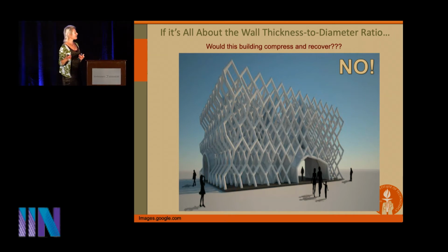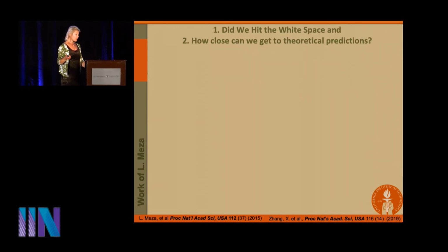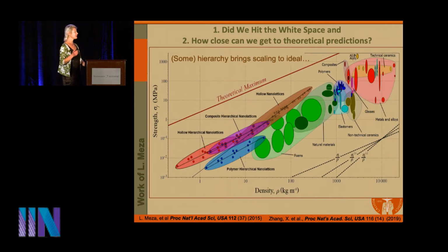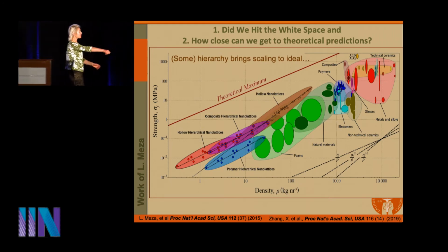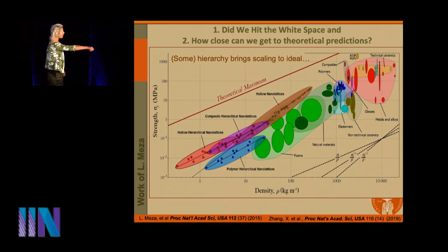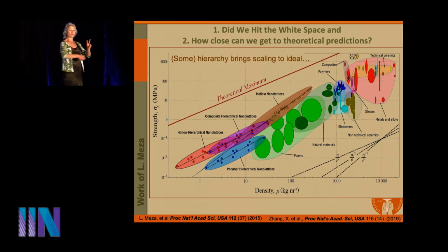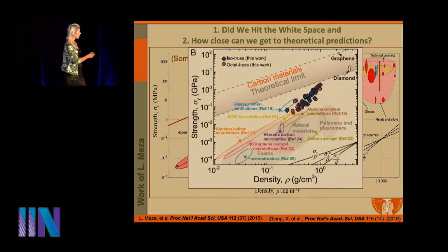All right, so now at this point, our questions were originally, did we hit the white space and how close can we get to theory? Just to remind you, this was the parameter space before, and these are all of our points that we've accumulated over the last few years, just on the hollow alumina. You can see, for example, that we already bought ourselves a 2 orders of magnitude reduction in relative density in the white space where people hadn't really been before, and perhaps some of you can do even better than that now. This was the first venturing out into the white space. Now we can do much better than this.